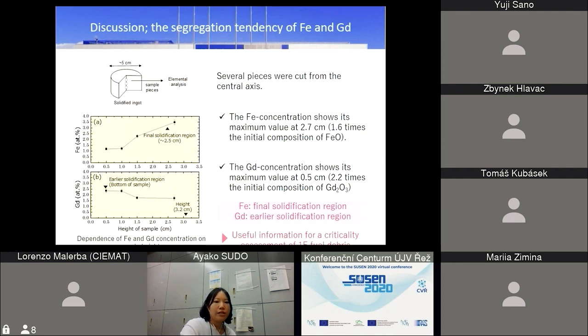So the experimental result indicates iron concentrates in the final solidification region, and gadolinium concentrates in the early solidification region. This segregation tendency of iron and gadolinium is very useful information for criticality assessment of fuel debris.